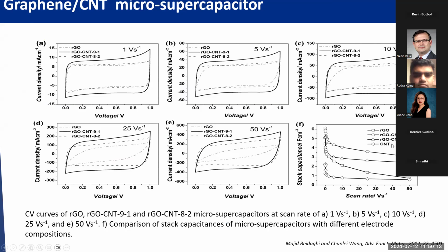And if you add CNT into this composite, CNT plays 2 roles. First of all, CNT can open up the RGO, so you keep the distance between the RGO sheets, for example, and keep the RGO without restacking. And CNT can also play another role by improving the electron transfer. Because the good electrical performance of reduced graphene oxide is on the same plane, but it does not cross different graphene planes. So by adding the CNT as a wire, you can really improve the kinetics between the RGO layers.